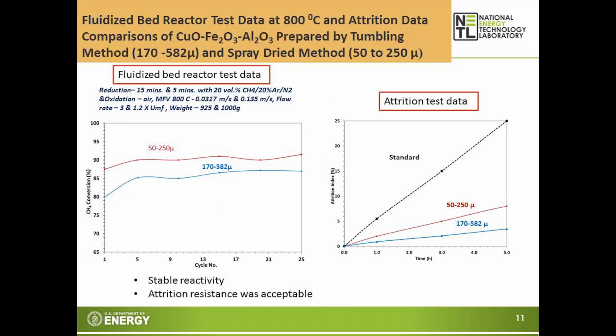These are some of the fluid bed reactor data at 800 degrees C with methane and air, and also some attrition data. Okay, we did test both particle sizes. As you can see, the methane conversion was very stable during the 25 cycle test with both these particle sizes when we conducted the test in the fluid bed. Okay, so we can see stable reactivity, and these are the attrition test data. And usually we compare the attrition resistance with the standard material that we use in the fluid beds. As you can see, both these copper oxygen carriers had a lower attrition index than the standard materials. So that means the attrition resistance of the copper commercial preparations was suitable for the pilot scale test.